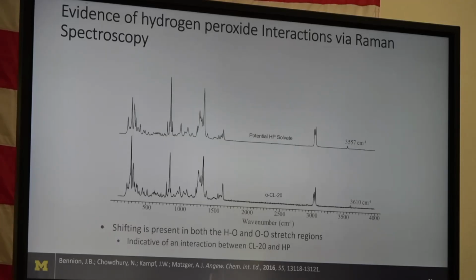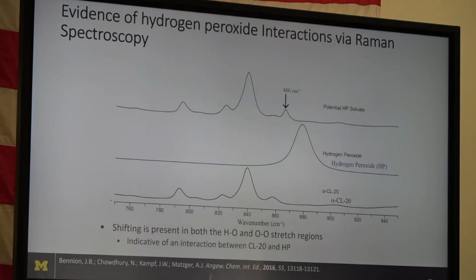So we did a lot of our initial screening with Raman spectroscopy, and we could see that when we were growing this out of hydrogen peroxide, we were seeing changes out here, consistent with changes in hydrogen bonding patterns. But also, with peroxide, you have an O-O stretch that's down around 880, and we were seeing that as well, that was occurring in the potential hydrogen peroxide solvate, but not in the alpha CL-20. So it looked pretty good, and so we were able to crystallize this.